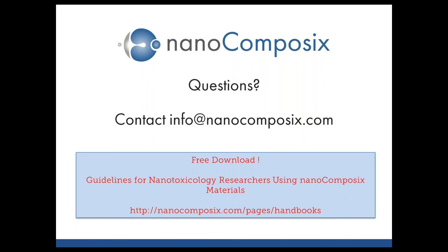Yeah, I think it's complex. Quat ammonium compounds are typically used for antimicrobial type of things, and I think it has to do with the effect of how some of those cations are interacting with materials. The basic thing that's seen is that most things in a biological system, for whatever reason, have a negative charge. And so if you've got a positively charged particle and it can actually stick or interact with the element of interest, then typically that particle, now that it's on the surface, has a higher chance of uptake, or if it's releasing silver ions, now it's releasing silver ions very locally to the surface of that entity and can induce a higher level of toxicity.